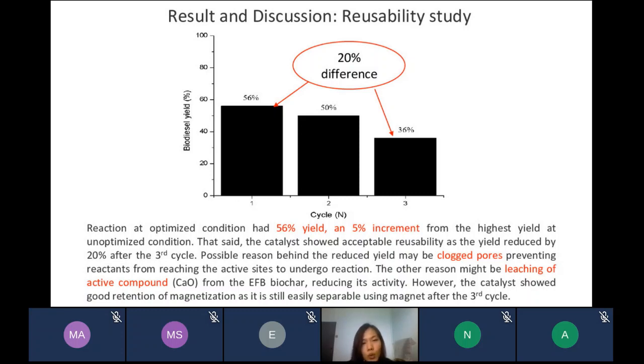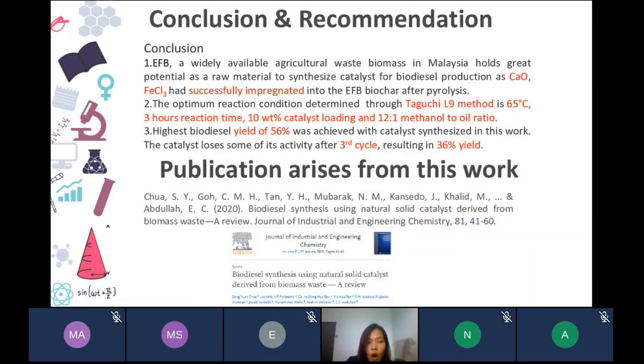Why? This is mainly due to the clogged pores. When the pore is clogged by the byproduct, which can be the glycerol, it can deactivate the catalyst itself. Or there is a second reason: it may be due to the leaching of the active site. Active site here is referring to the calcium oxide at the surface of the catalyst, which has caused the reduction in the biodiesel yield. Okay, so move on to the conclusion and recommendation.